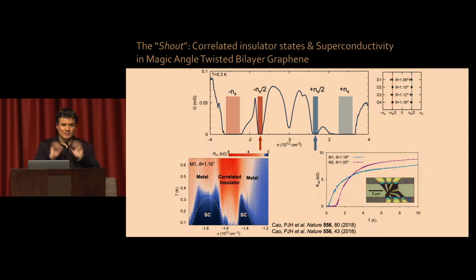And all of this happens only at 1.1 plus minus 0.1 degrees of rotation between the sheets, okay? It's a very tuned behavior, magical almost. I think the term magic angle graphene was invented before they saw this thing, but it is even more magical now that we saw this thing.